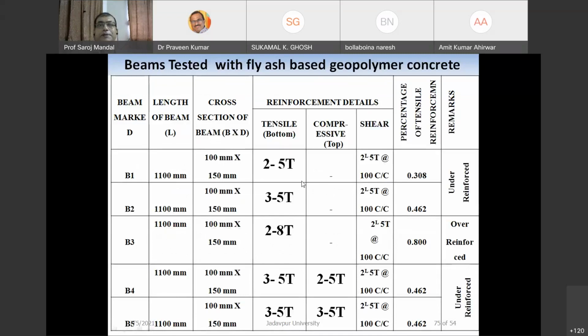That is your beams. We are using 5 beams, right? Then in the tension zone, we are using 2 numbers of 5 diameter bars, 3 numbers of 5, and 2 numbers of 8. This has been used to make the section under reinforced. These are 2 sections. These are basically under reinforced, and this becomes over reinforced, right? Similarly, for this 3-5T, we use compression reinforcement. In this case, we don't put any compression reinforcement. We just put some wire. In this case, we use 2 numbers of 5 and 3 numbers of 5. That is, both are under reinforced, right?